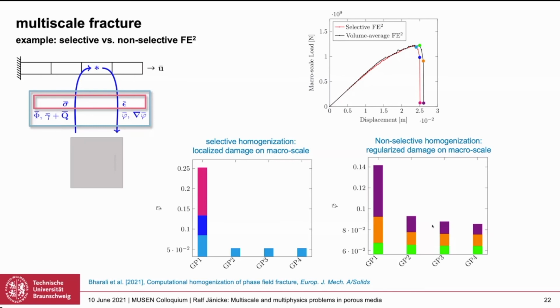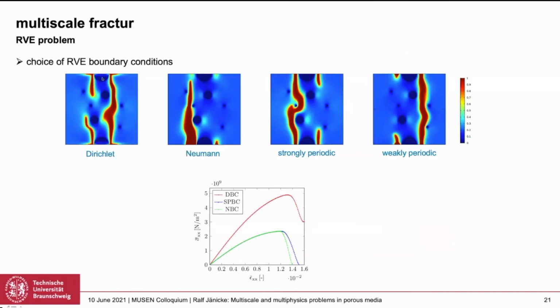What is interesting here is that on the small scale, we associate full damage with the damage parameter being equal to 1, whilst this is not the case here. Here, full damage means damage is equal to 0.25, and for the non-local model, it's even lower. The reason is how this phi bar is computed. It's the volume average of the damage in the RVE. And if I have a crack passing through the RVE, the volume fraction of this crack is, of course, smaller than 1.